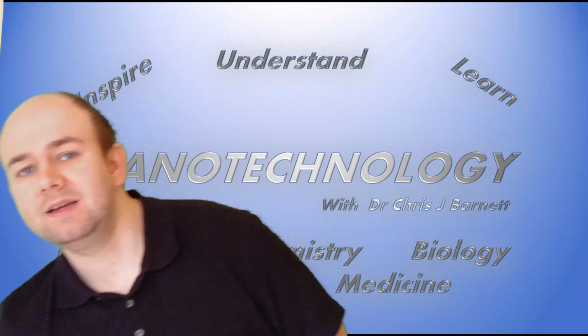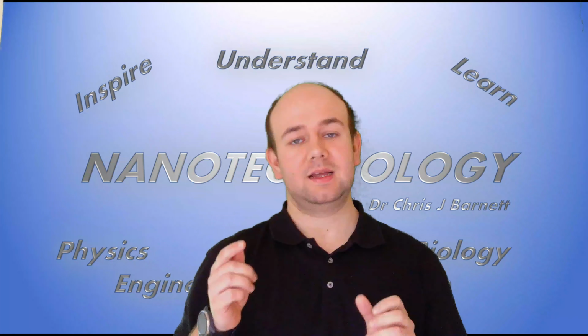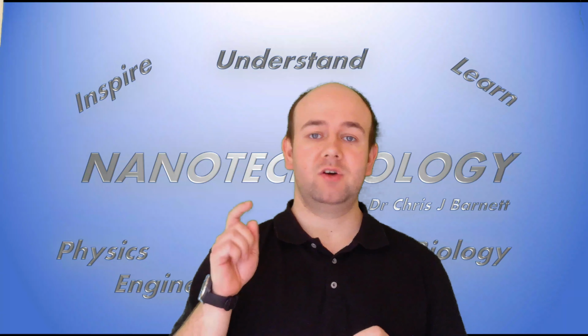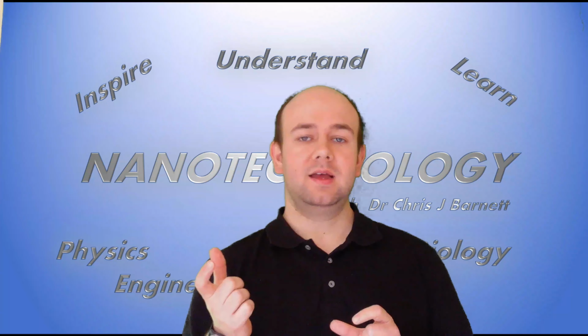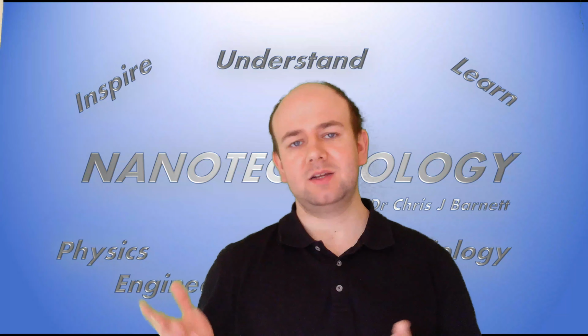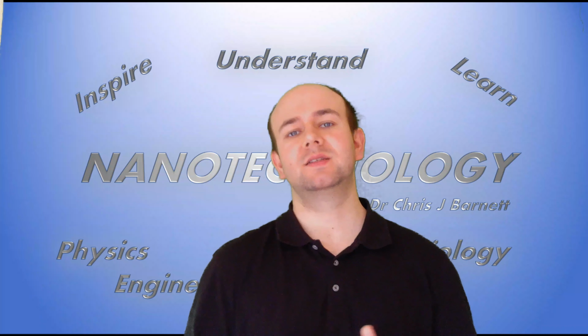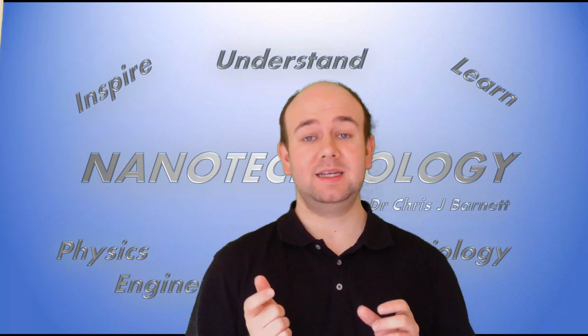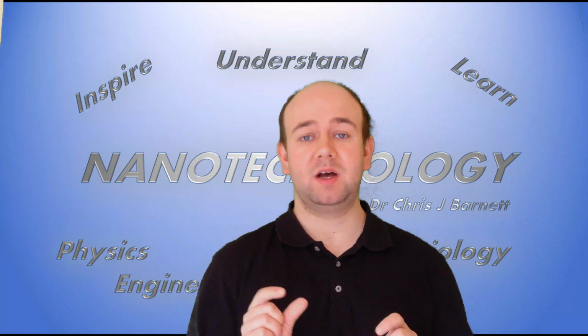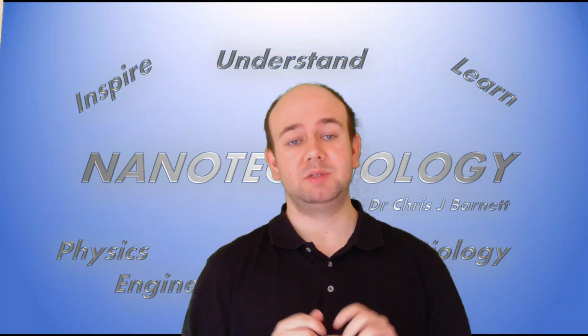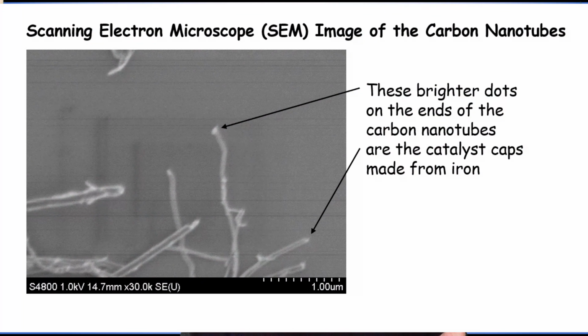So this work really focused on flowing electrons, or electrical current, from the catalyst end of a carbon nanotube into the main body of the carbon nanotube. These nanotubes were grown in a furnace using an iron seed. These are small nanoparticles of iron, and they act as a nucleation site for the carbon nanotubes to grow out of. So quite a few of our nanotubes have this iron catalyst cap on the end of them.